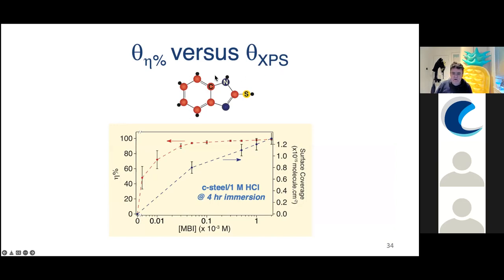We've done that for this molecule MBI on carbon steel in one molar hydrochloric acid, after 4 hours immersion. On the left-hand side, the red data points show the efficiency. You see it's a highly efficient molecule, almost approaching 100%, about 98%. And on the right-hand side is the surface coverage determined from XPS. We've then translated both of those to thetas, to fractional surface coverages, for both inhibition efficiency and surface coverage, where we've assumed this coverage here is theta equals one.